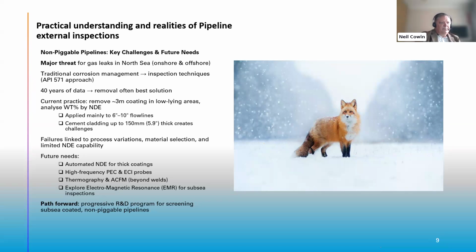I've had to go in, strip the riser, and find them with practical UT, which one of them was a 45-year-old 8-inch line. It was a very small bore line. And it holed on me, but it was basically at pressure below 3.5 bar that we found that defect. So there are instances where you will miss defects with MFL.